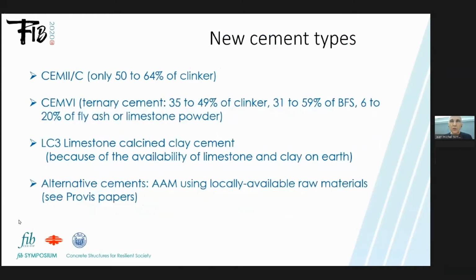We have new cement types in Europe. We will have CEM II/C, meaning that we have only 50% of clinker, and another component, mainly limestone, for instance. We expect to have a CEM VI cement, ternary cement, with less than 50% of clinker, and with blast furnace slag and fly ash or limestone.